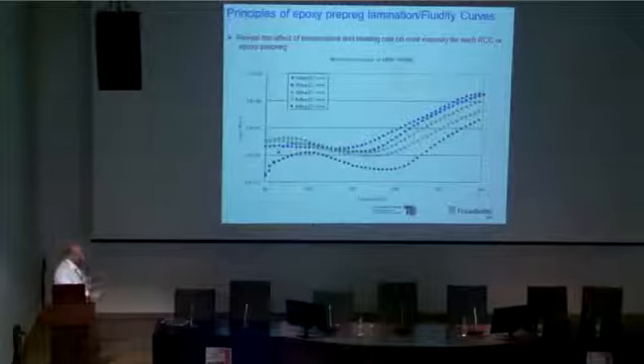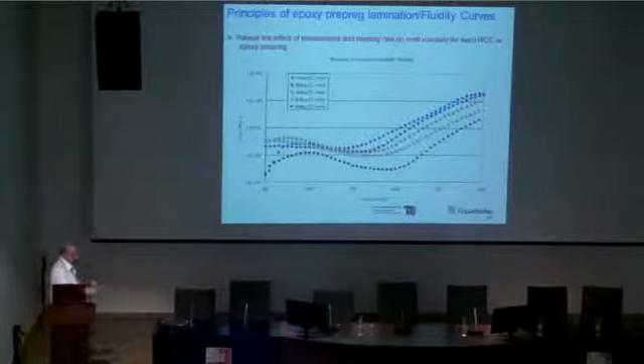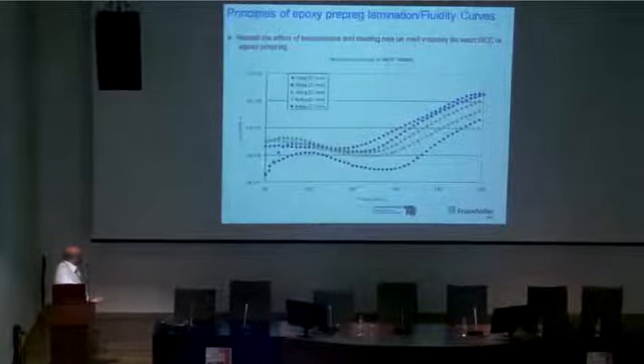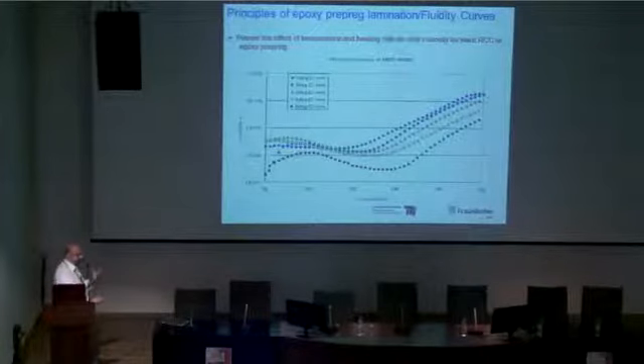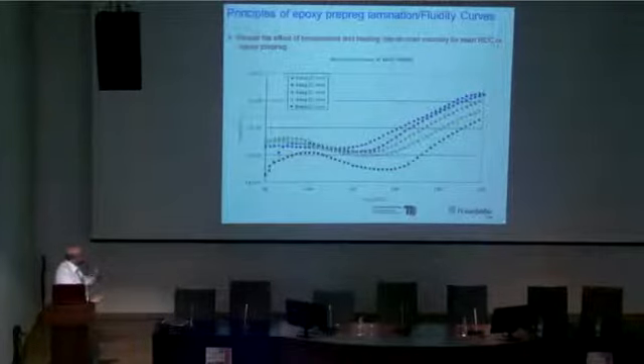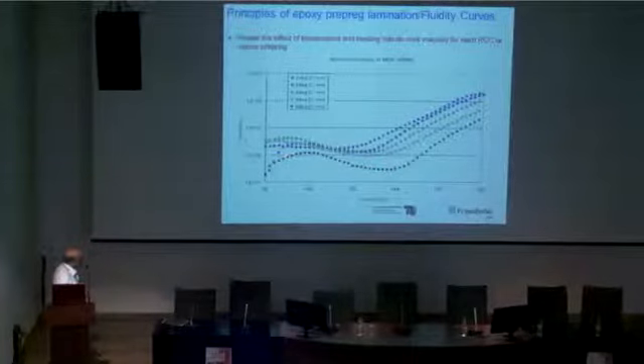Let me back up a little bit in order to give you the whole view, how we do the lamination. So this epoxy prepreg, as I said, is in a B-stage format. So we buy it in a B-stage format. You can refrigerate it. You take it out. When you start increasing the temperature, this starts melting, okay? So apparently the viscosity will increase a little bit, but about 80 to 100 degrees Celsius, the viscosity will start decreasing. And as you will see, it reaches always a point of minimum viscosity.